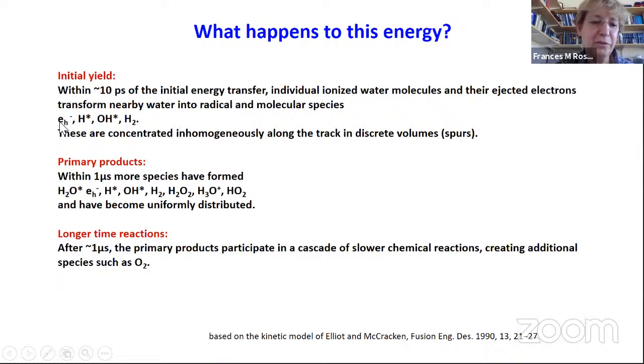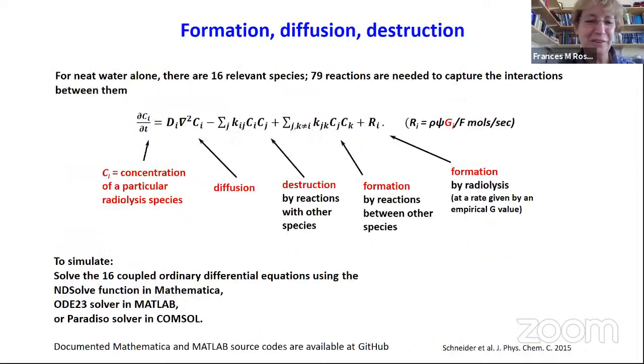This is the hydrated or solvated electron. And along the track of the electrons, they react with themselves and with more water to get more species. These all diffuse around and get uniformly distributed locally. And then after longer time, you get secondary reactions to form things like oxygen. So this is very well known for water. Notice that there's nothing apart from water in this. I'm not talking about electrolyte, I'm just saying plain water for now.